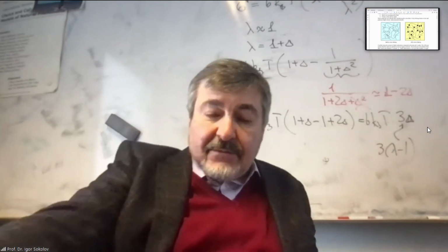It doesn't flow when the stress decreases below some limit. And here, this guy essentially flows under whatever stress, however, extremely slowly, if the stress is small. This is essentially a fluid or a viscoelastic material.